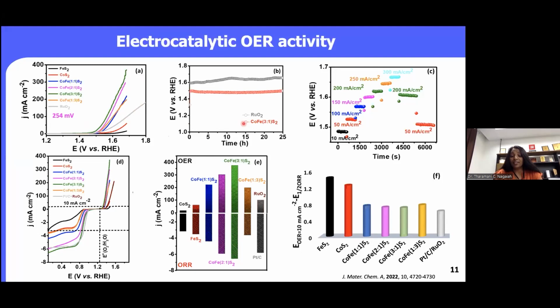And if you do the stability test, it is quite stable, similar to the ORR as well as HER, and also you can see that there is a fluctuation with respect to the ruthenium oxide. It is very important to understand the tolerance of the material at various current densities. So to understand this, we have performed chronoamperometric experiments at various current densities, and even jumped up to 250 milliamp per centimeter square. And again, when we shift back to the 250 and also the lower current density, the potential almost retained its potential. And now, yes, our catalyst is good towards the OER as well as ORR.